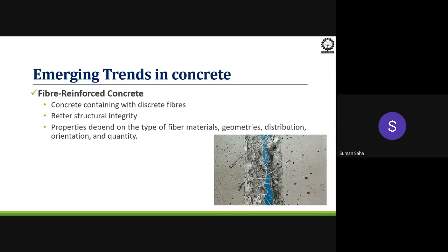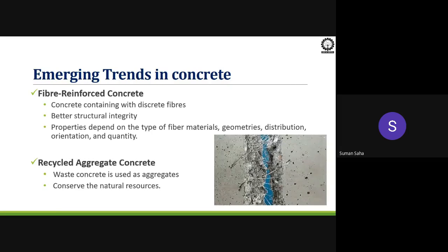You can see here, this specimen is after testing. When we are doing the flexural strength test, you just type the test for flexural strength of fiber reinforced concrete, and you will get the detailed procedure of the test. If it is normal concrete, it will crack easily, but due to the fiber, the load carrying capacity will be increased. As a result, the total overall structural integrity of the concrete structure will increase, and it will give us better service. Next, recycled aggregate concrete.